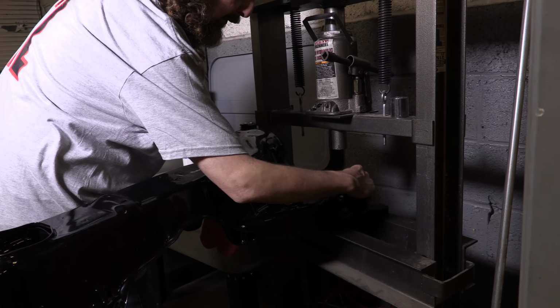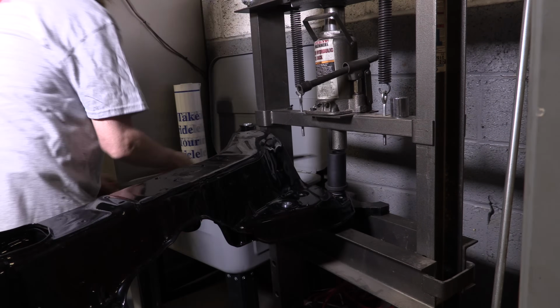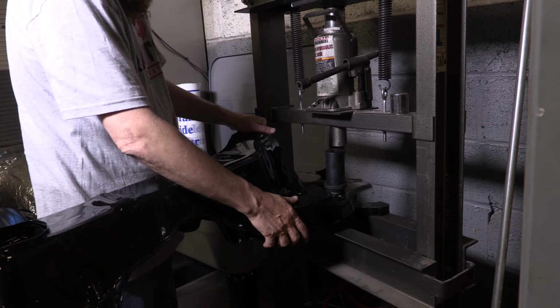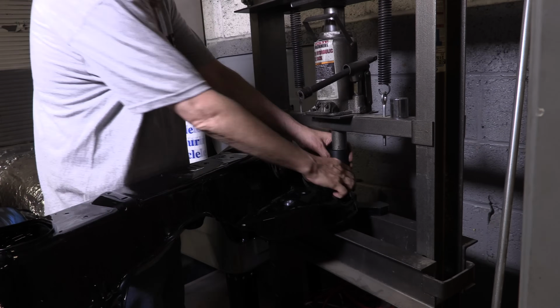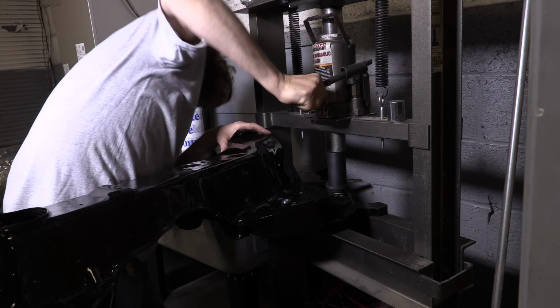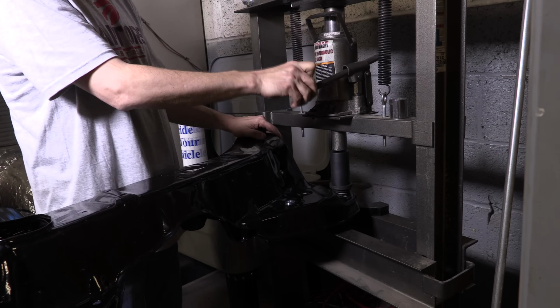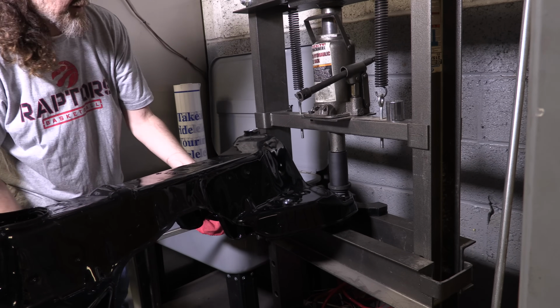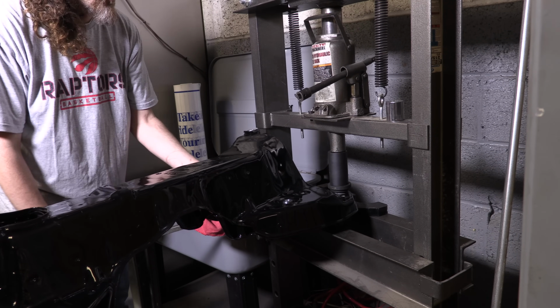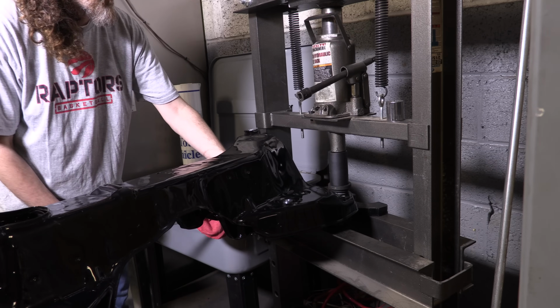Without the first half hour of video, the only thing that I can guess went wrong is the subframe contacted the press frame as the bushing was coming under load, preventing it from pressing the bushing in straight. As it advanced, it only got worse, but it bent the boss that was only halfway welded to the subframe, and I'll show you that.